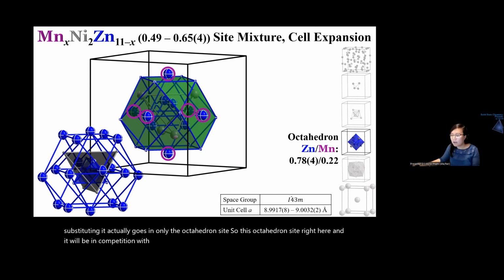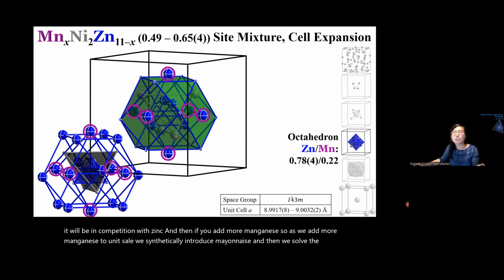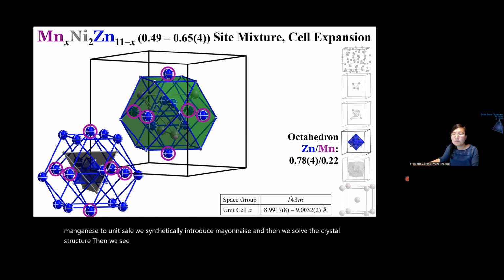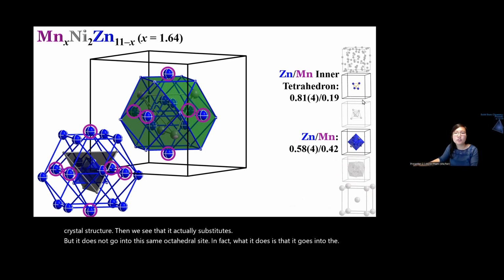And then if you add more manganese, as we add more manganese to a unit cell, we synthetically introduce manganese and then we solve the crystal structure, then we see that it actually substitutes, but it does not go into the same octahedral site. In fact, what it does is that it goes into the inner tetrahedron. So you see this inner tetrahedron right here. So manganese doesn't ever fill up this site. It goes into a completely different site.